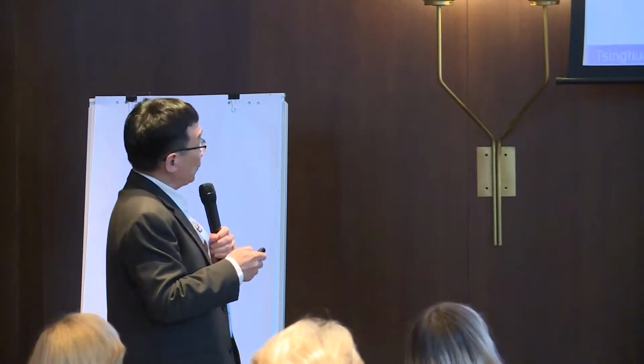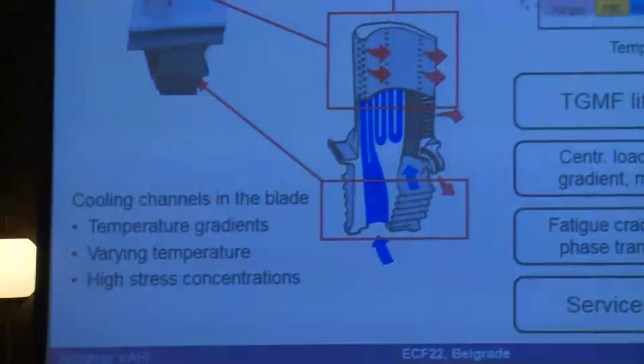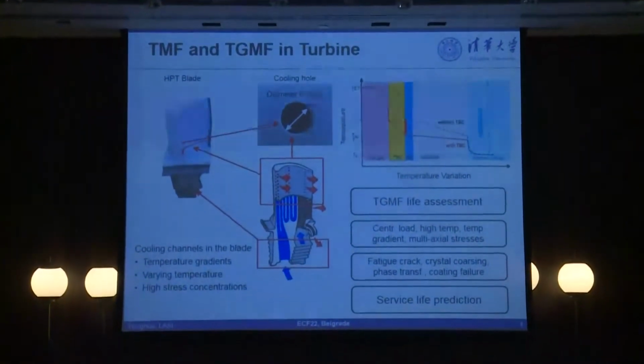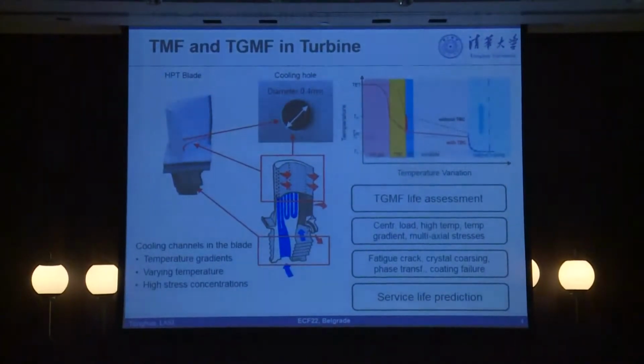As I said, I work on aero engines. If we talk about aero engines, we know the temperature is very high. In the combustor the temperature already exceeds 2,000 degrees C, but the material temperature cannot be so high. Actually all aero engines use so-called nickel-based alloy. What you see here is the high-pressure turbine blade. This material is single crystal nickel alloy. That material can be used up to 1,000 or 1,100 degrees C, the highest temperature we can use. As I said, the environmental temperatures are around 2,000 degrees C. Therefore, we have almost 1,000 degrees C temperature difference between the environment temperature and the material temperature.